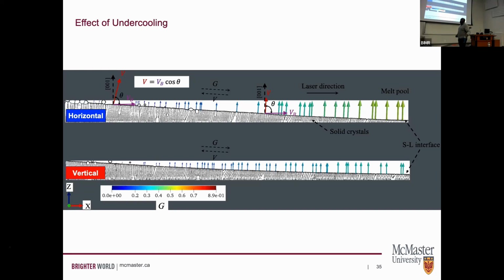We also looked at the effect of undercooling. So in solidification, what determines, particularly for this columnar to equiax transition, those localized equiax grains that grow is how undercooled that liquid is ahead of that moving solid front. So not only are we seeing different epitaxial solid profiles that have formed, that also informs the nuclei that form, because the liquid ahead of that front has changed in terms of its temperature profile.